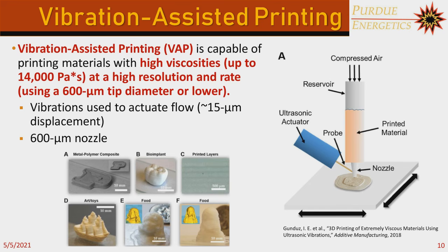Well, at Purdue, we developed a custom technique called vibration-assisted printing. What's unique about this technique compared to other methods out there, and there are many methods out there, is that we have the ability to print viscous mixtures, in particular, viscous heterogeneous mixtures, which is exactly what propellants are. And we can do it at a relatively fast rate and with a relatively high resolution.